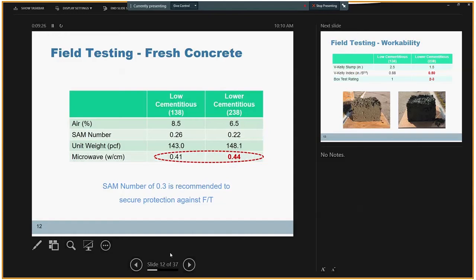The only issue we observed here was in the data from the microwave test to determine the actual water cement ratio of the concrete. For the concrete with lower cementitious material content, we observed that the actual water cement ratio was 0.44 compared to the design value of 0.42.